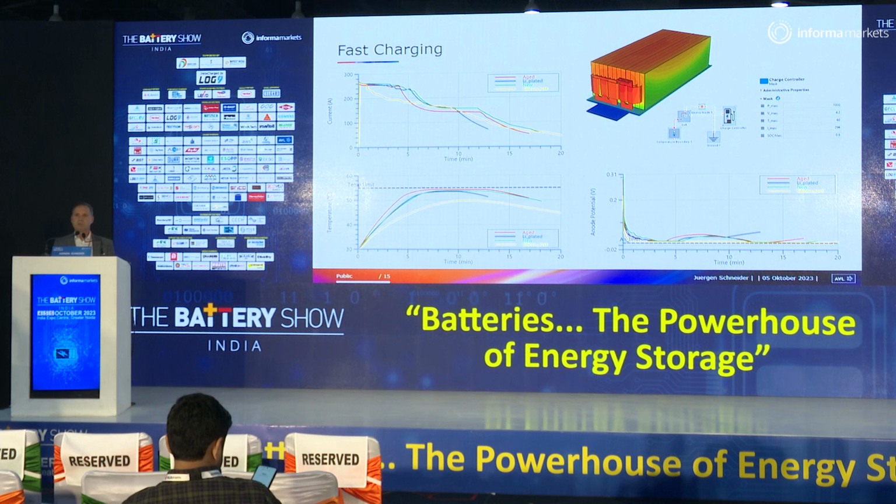And as you can see, if this anode is aged, if the graphite is aged, then you get problems: it runs into lithium plating because it has reached the anode potential limit quite fast. Therefore, you would stress or damage the aged cell even more. So already here, you can use simulation to develop individual BMS strategies for different cell categories and aging states.